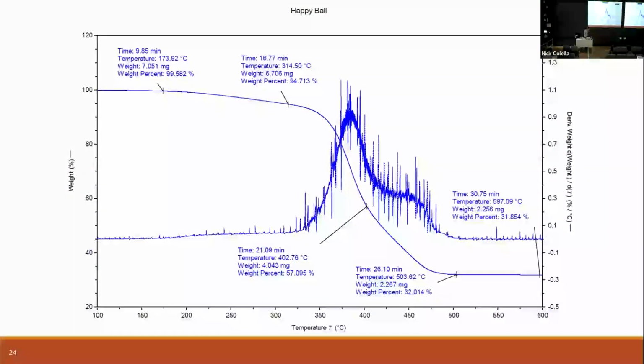So this is typical TGA data. This is for the happy ball. I'll close that label covering it up at the top here. So this is the TGA data for the happy ball, and we see basically 2 or 3 decomposition steps. So we see as we heat up to 600 degrees, how much mass do we lose? At 170, we have 99% of the weight still. So that tells us that we have very low water content, right? Which is what we'd expect, but good to confirm.